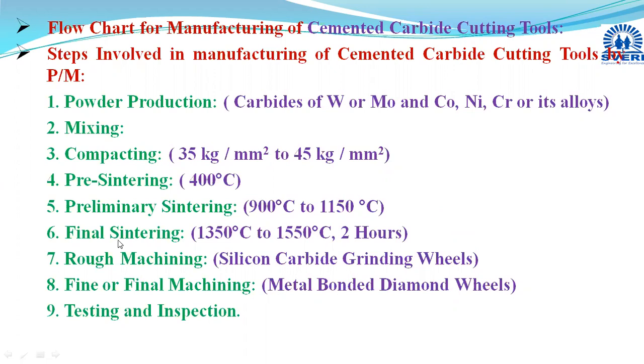Sometimes before doing this final sintering, after preliminary sintering, some machining or sizing operations can be performed. After preliminary sintering, some changes are there, and some size rectification, sizing or machining operations can be done, and then it is given to the final sintering. While manufacturing only, we will try to manufacture the component with oversize, so that after the final sintering we will get the component with the required dimensions or near to the required dimensions. Then in this final sintering, diffusion of cobalt will take place, and cementation of the tungsten carbide or molybdenum carbide particles will occur.